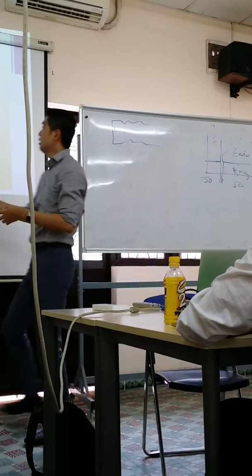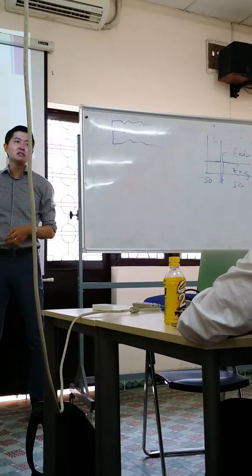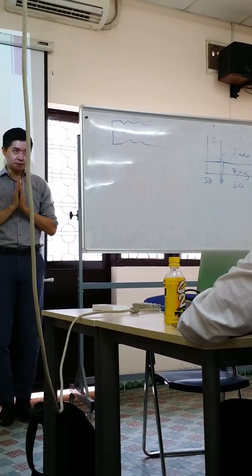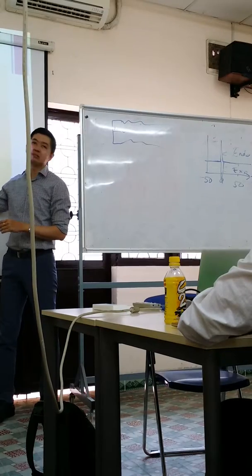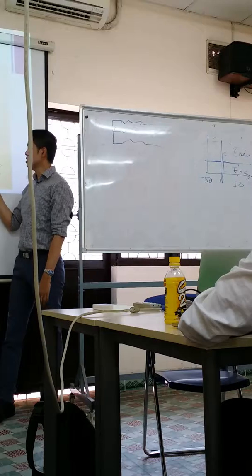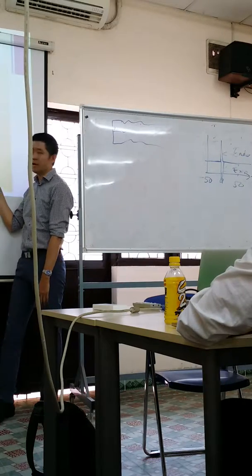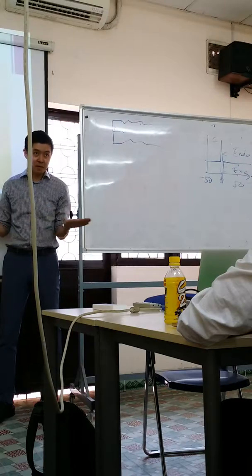So these are alpha, we call it vertical oscillating chain. Vertical, okay, straight line. You have beta prime tilted chain, it's tilted a bit. This one also tilted chain, but every zigzag, this one is the same plane, same dimension.